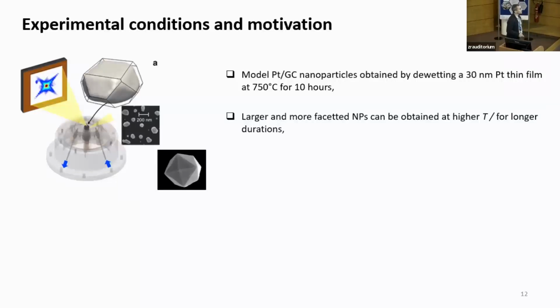We work on model platinum nanoparticles that we obtain by dewetting a thin film. So we dewet this thin film at 750 degrees for 10 hours. We can control more or less the size of the particle by changing the temperature of thermal annealing or by changing the duration of the thermal annealing. Well, in the end, on the surface we have particles 300 nanometers in size, smaller, larger, and this is kind of convenient because then we can choose which particle is best adapted to our experimental conditions.